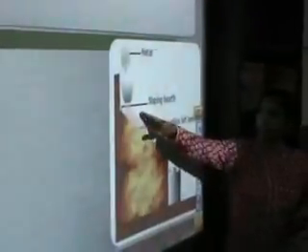This is a furnace, alright, wherein you can see that there is a sloping hearth. The impure metal which you are having, either tin, lead, bismuth, etc., we sometimes call it the charge. Now from here you will heat and maintain the temperature in such a manner that you keep in mind the melting point of the metal which you are going to purify by this particular method, and we will keep it just slightly, very very little above the melting point of the metal which you want to purify. You will maintain the temperature.